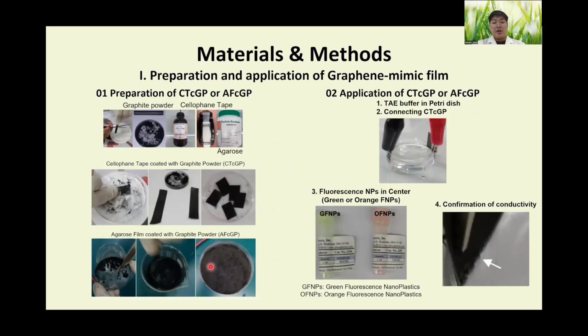I prepared a graphene mimicking film called CTCGP or AFcGP by coating graphene powder onto Cellophane Tape or agar rolls. And then I confirmed the film's electrical conductivity by the bubble formation on its surface when electricity was applied to the film in the solution. Also, I used the film as an electrode to examine the electromobility of the fluorescence nanoplastics.